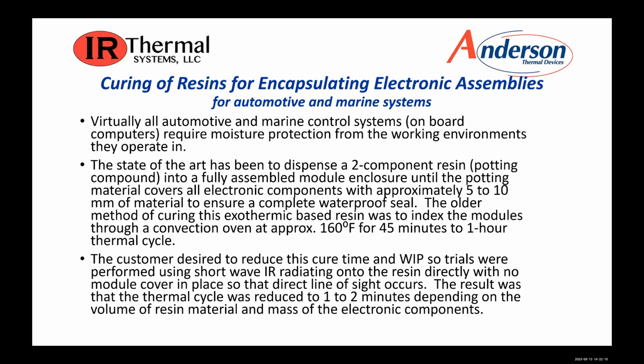chemistry is such that you have a resin and a catalyst, very similar to fiberglass, where you mix the two and it will harden over time. By utilizing the infrared, we were able to get the thermal cycle down to 1 to 2 minutes, depending on the shape and the volume of the resins and mass. This is very successful. Again, it's pretty much widespread throughout the industry.